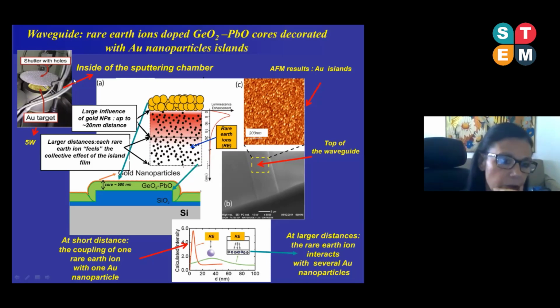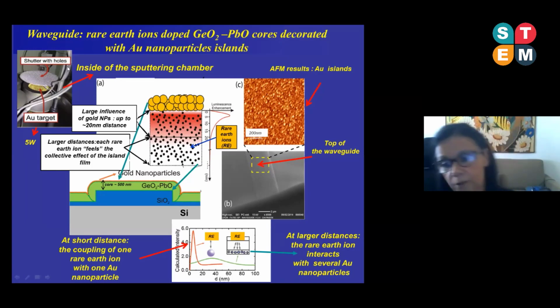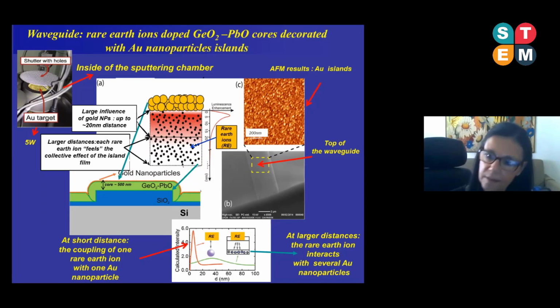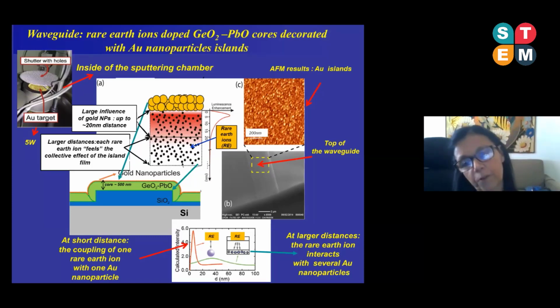In this figure, I show you the inside of this sputtering chamber, the target of gold, a commercial one, and we place above it a shutter with holes. This is done in order to reduce the rate of gold that is deposited. A lot of gold compromises the guidance. We also use a very low power of about 5 watts, and the deposition of gold is performed for a short time. All of this is done in order to avoid a lot of gold.